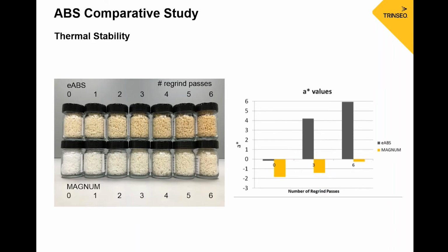So then we also looked at thermal stability. We did a repass study in a twin screw extruder with the emulsion ABS, which you see in the vials on the top, and then with the mass ABS in the vials on the bottom. And you can see the color change as it took place with each pass.